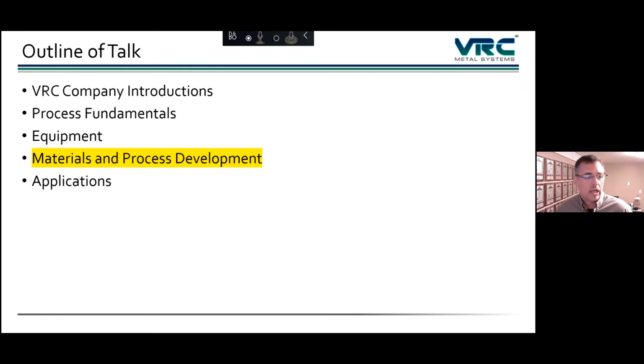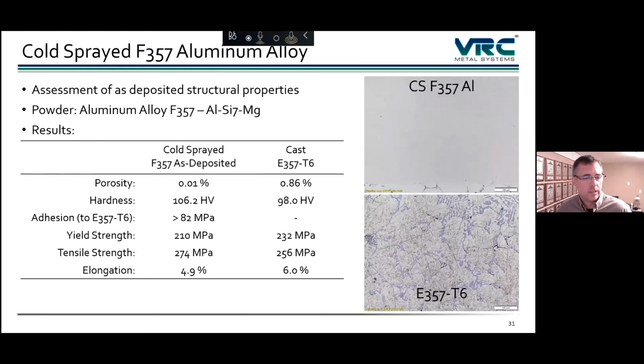So with that, I'm going to talk a little bit about materials and process development. This is going to get into properties of many of these materials. This is an example of an F357 cold sprayed material repairing an E357 substrate. In this case, you can see the mechanical property differences here. The strength of the cold sprayed material is actually a little bit higher. The tensile strength is a little bit higher, even though the yield strength is a bit lower. But the ductility is pretty close between the F357 and the E357. So in this case, we're applying a material that's relatively comparable in properties.